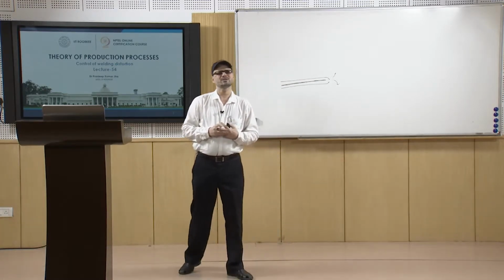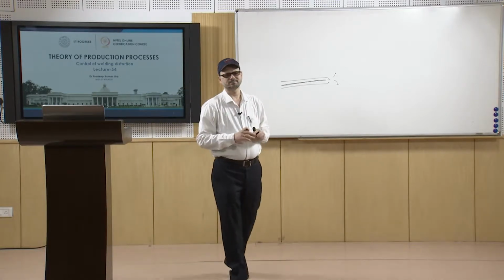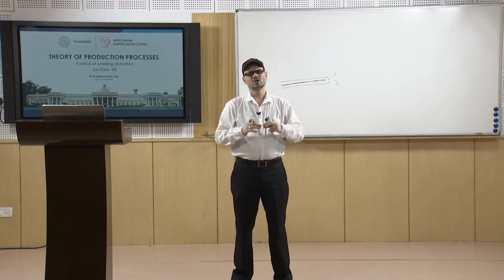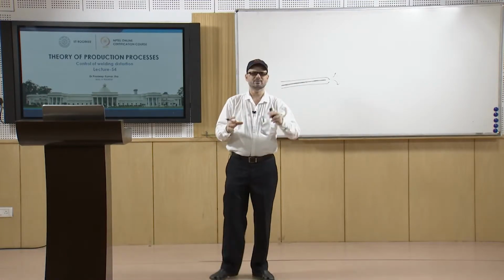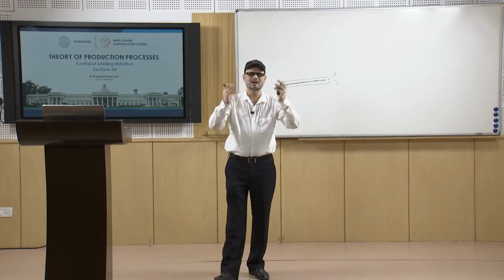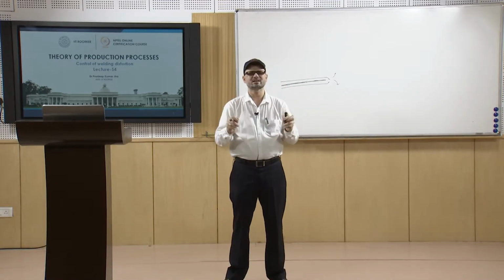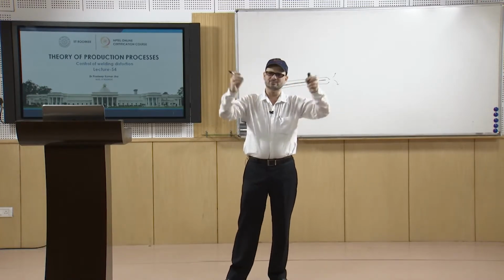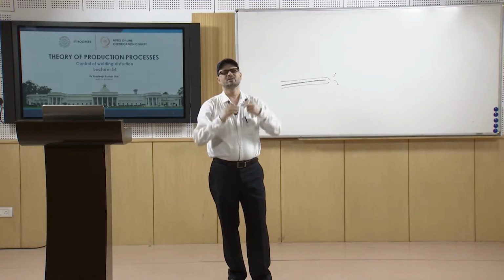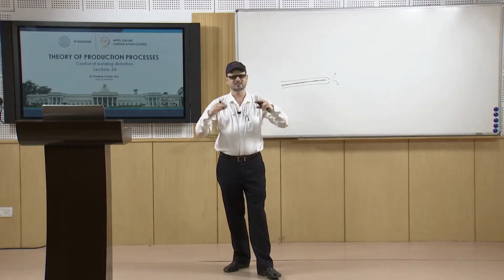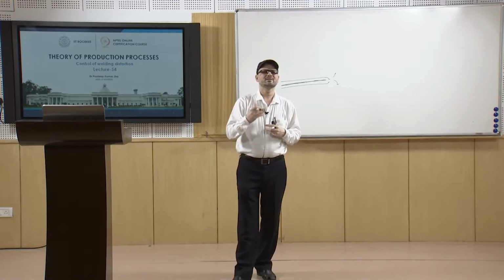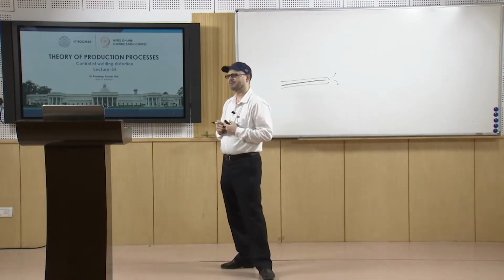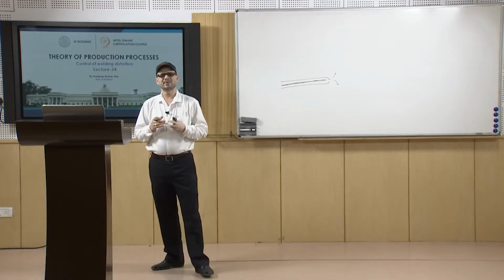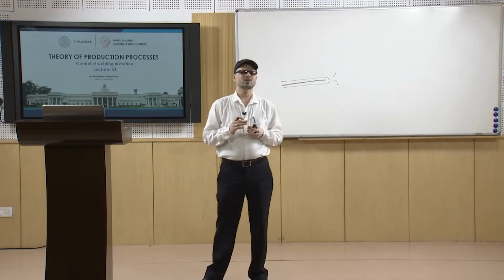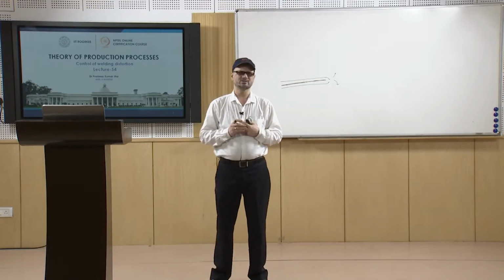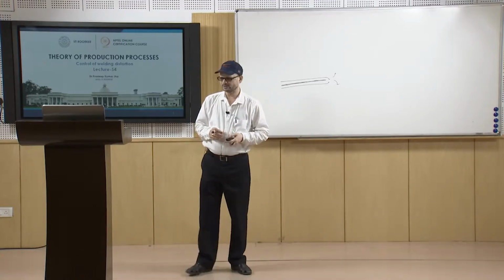Many a times you have a counter setup. So, many a times what happens is that the welded structure bows, or it has a sagging type of tendency in one direction. So, you are trying to have a counter setup. So, suppose it bows in this direction. So, you put the specimen itself in the opposite direction, so that even if there is a bowing or so in certain direction, then it will be flat even after the welding. So, this way you have the different types of methods which are there for controlling the distortion in the welds. So, we will discuss one by one all these methods.